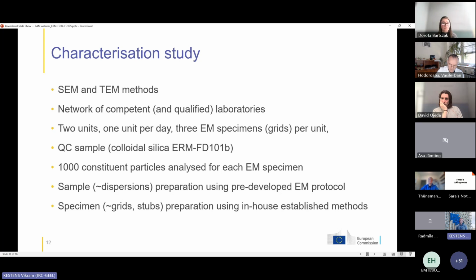So many laboratories need to measure powder nanomaterials nowadays, but from expert laboratories, we were only able to find a few laboratories who were able and willing to measure the materials. This also highlights the complexity and the many challenges related to measuring nanoparticles when they are in powder form. Again, we provided the laboratories that participated in the characterization study with the measurement protocol that we developed. Along with that, we also provided some quality control samples, which was a former colloidal silica certified reference material.